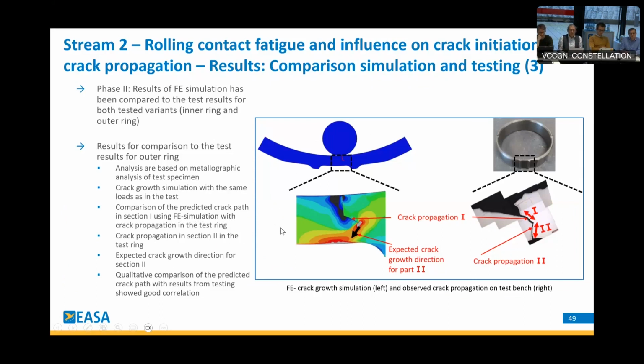So this was expected. Now you see the crack propagation phase 1. This is meant with 1 and 2 in the wording here, and we have a direction change at the end, which is part 2. If you would put this on top of each other, you could say again, it's a good qualitative correlation between the simulation and the testing. Of course, it's cut and arranged, but qualitatively, I think the depth and also the direction fit quite well.